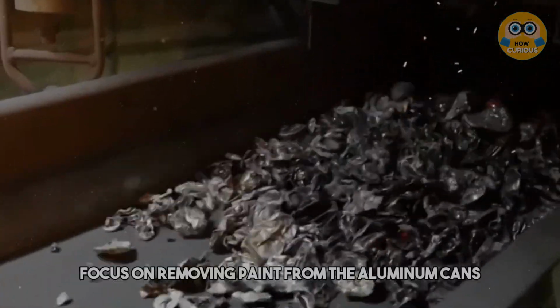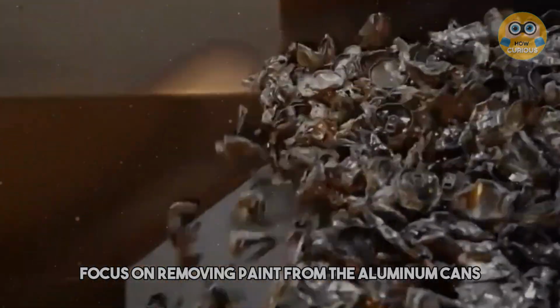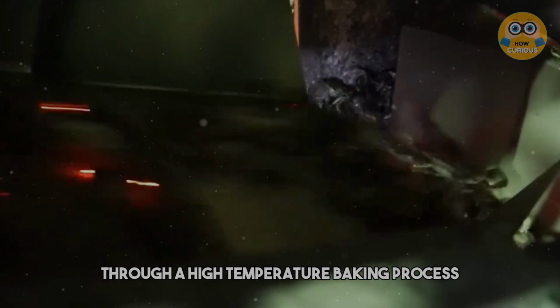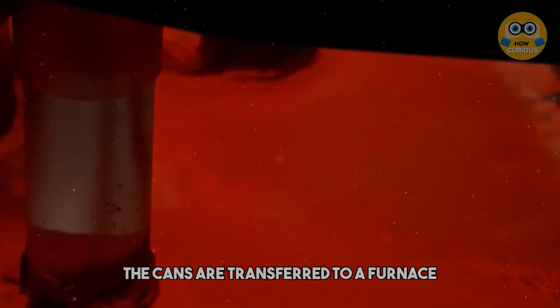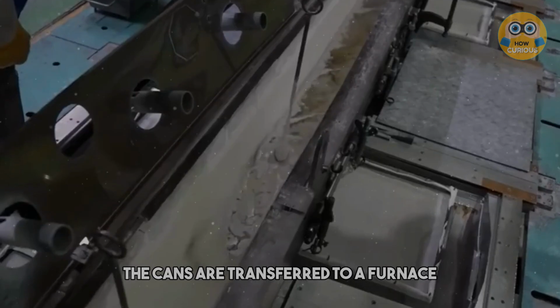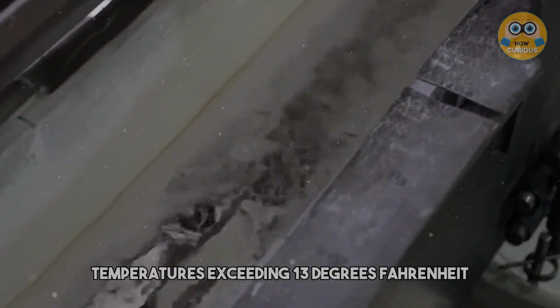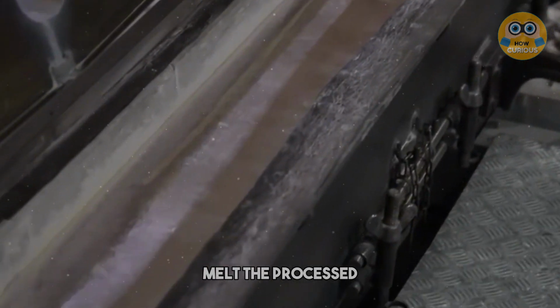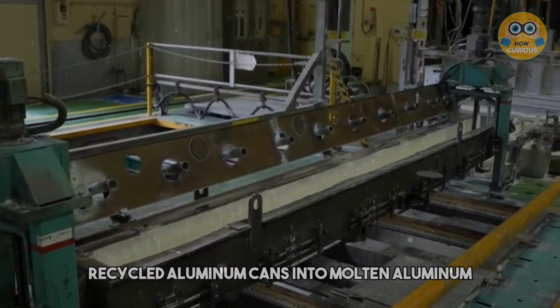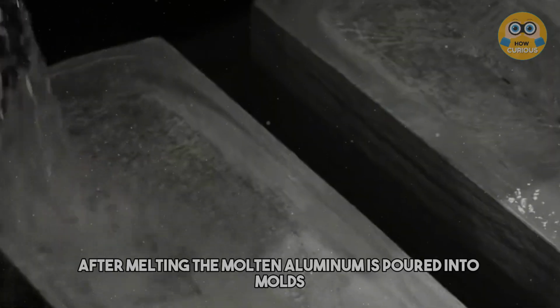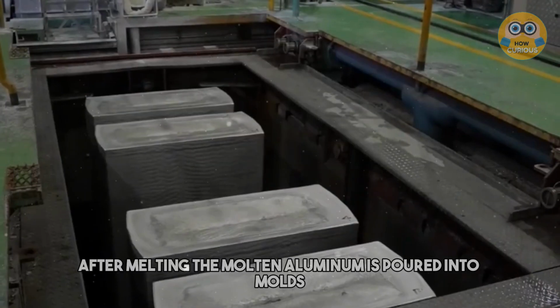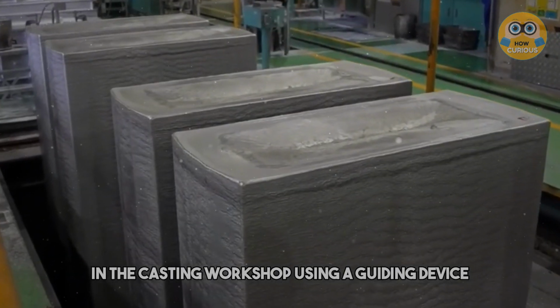The first 9 focus on removing paint from the aluminum cans through a high-temperature baking process at 400 degrees Fahrenheit for half an hour. Once cleaned, the cans are transferred to a furnace. Inside the furnace, temperatures exceeding 1300 degrees Fahrenheit melt the processed recycled aluminum cans into molten aluminum. After melting, the molten aluminum is poured into molds in the casting workshop using a guiding device.